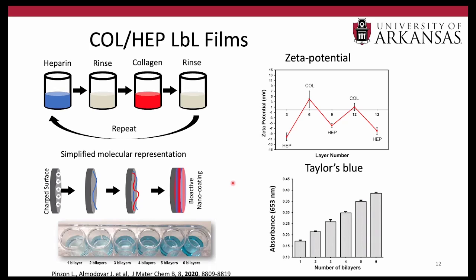All right, so I'll talk a little bit about layer by layer films. So again, how do we do them? We work a lot in cell culture with multi-well plates that look as shown here. The way we construct the layer by layer films on these plates is that we add to the well one of the polymers, say heparin. We let it absorb for a couple of minutes. We remove it. We add a rinse without any polymer. Rinse it a few times, remove it, and then we add the collagen and let it wait a couple of minutes for the collagen to absorb. And then we remove it, then we rinse, and then we repeat over and over again.